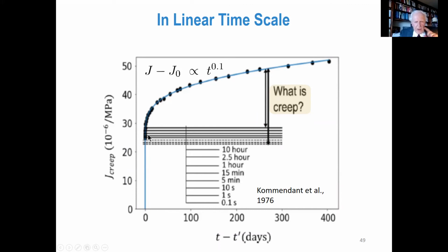Please note here one aspect. What is creep? If you use a hydraulic setup, open a valve suddenly, then the specimen is loaded within 1/10 of a second or less. If you do it manually, which is widely used by spring type apparatus, that may take 2 hours, even more to set up.